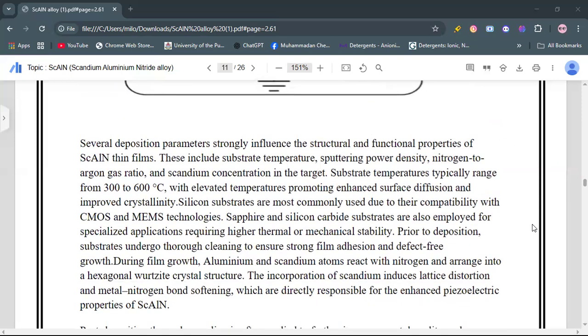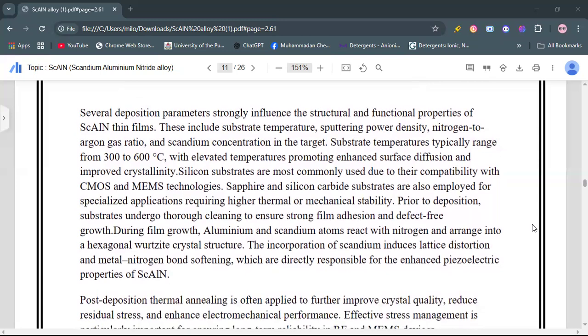Several deposition parameters strongly influence the structural and functional properties of scandium aluminum nitride thin films. These include substrate temperature, sputtering power density, nitrogen to argon gas ratio, and scandium concentration in the target. Substrate temperature typically ranges from 300 to 600 degrees, with elevated temperature promoting enhanced surface diffusion and improved crystallinity. Silicon substrates are most commonly used due to their compatibility with CMOS and MEMS technologies. Sapphire and silicon carbide substrates are also employed. Prior to deposition, substrates undergo thorough cleaning to ensure strong film adhesion and defect-free growth.